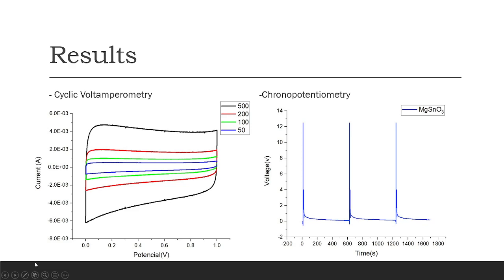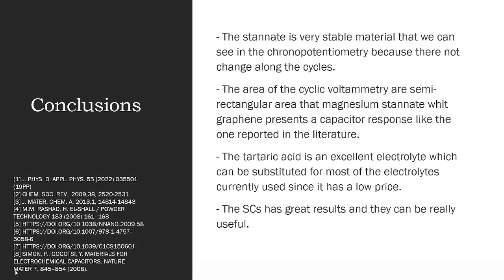Conclusions. The stannate is very stable material, as we can see in the chronopotentiometry because it does not change along the cycles. The area of the cyclic voltammetry is semi-rectangular. Magnesium stannate with graphene represents a capacitor response like the one reported in the literature. The tartaric acid is an excellent electrolyte which can be substituted for most of the electrolytes currently used since it has a low price. The supercapacitor has great results and they can be really useful.